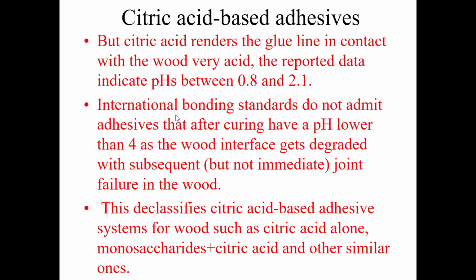And it is the following. Citric acid renders the glue line in contact with the wood very acid. Data indicates pHs of 0.8 and 2.1. The international bonding standards for wood do not admit adhesives that after curing have a pH lower than 4, as the wood interface gets degraded by hydrolysis, with subsequent but not immediate joint failure in the wood.